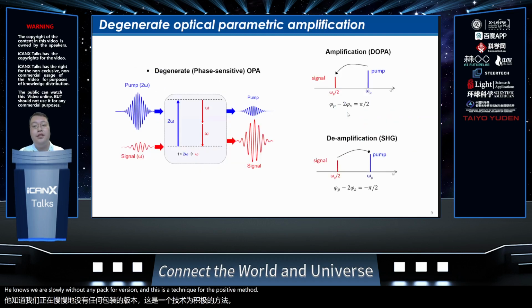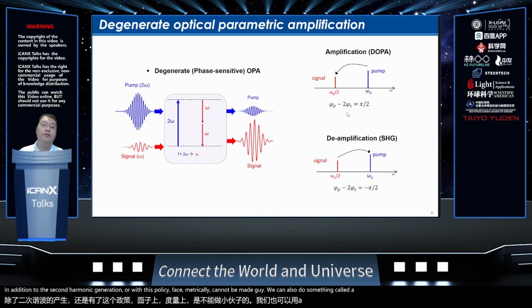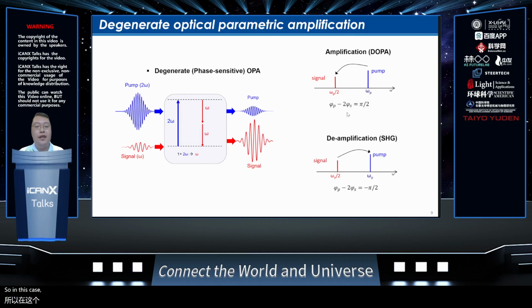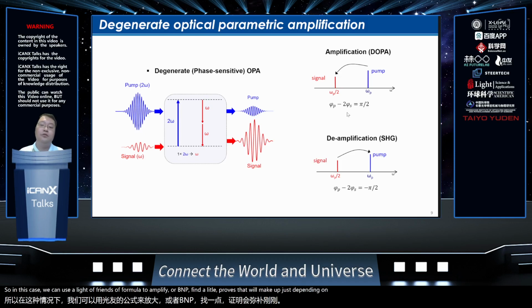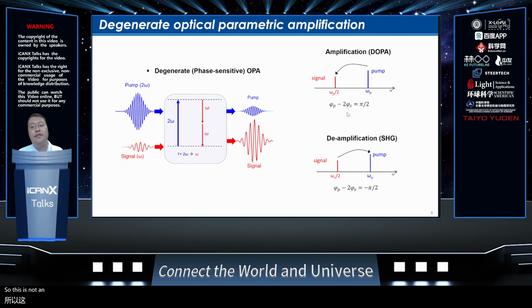In addition to second harmonic generation, with this quasi-phase-matched lithium niobate waveguide, we can also do something called degenerate OPA, which is very similar to the reverse process of second harmonic generation. In this case, we can use light of frequency 2 omega to amplify or de-amplify light of frequency omega, depending on the relative phase between the pump and signal. This nonlinear process is very well known already.